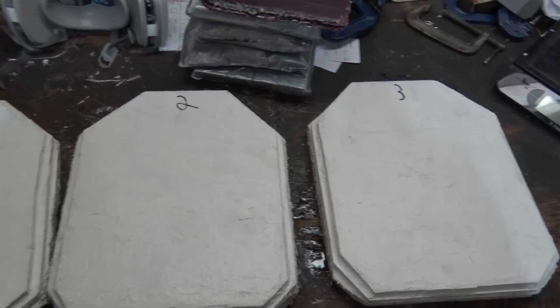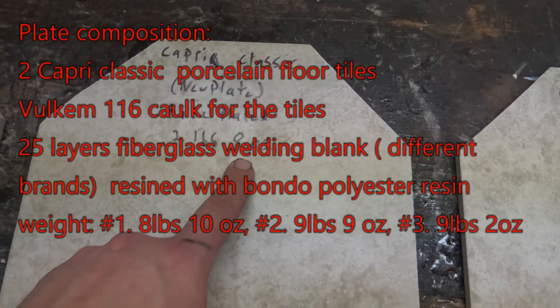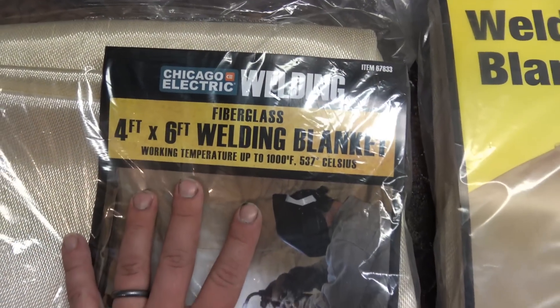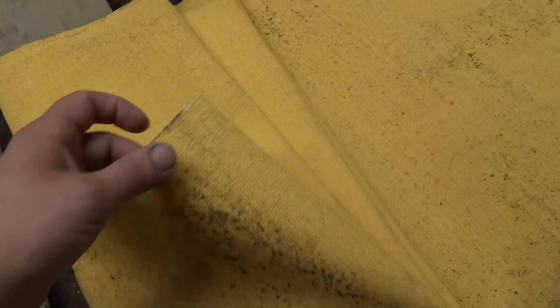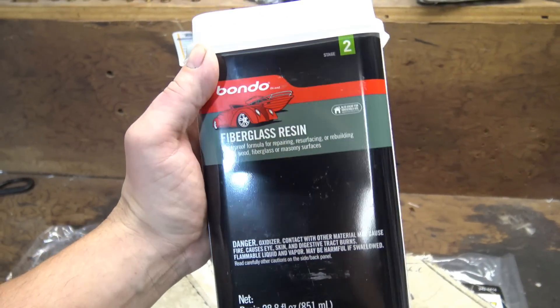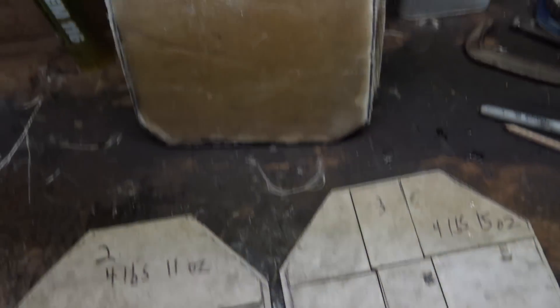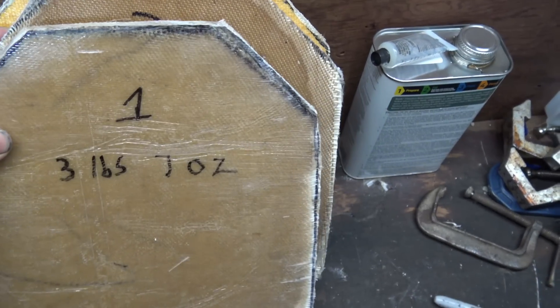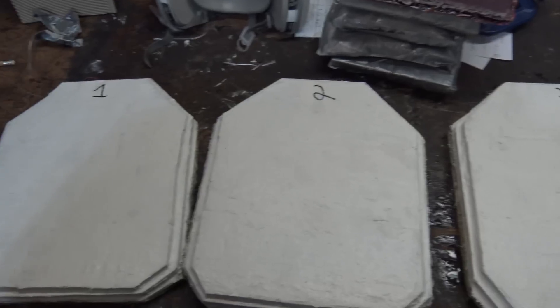The three plates were constructed with basically the same materials: porcelain coated with an elastomer resin for the strike face, and fiberglass welding blankets impregnated with polyester resin for a backer. The only real difference was the welding blankets — I chose three different brands to see how that would affect ballistic performance, which ended up affecting both resin consumption and overall weight. I also want to mention ZNA Productions' fiberglass welding video as the inspiration for these backers — I believe in giving credit where it's due. I'll provide a link in the description.